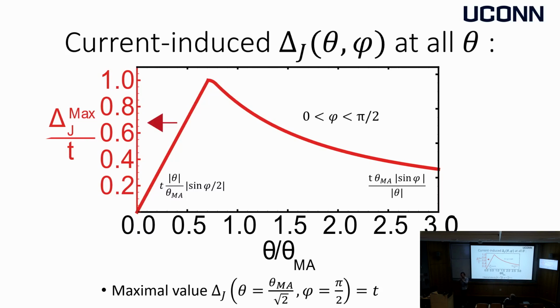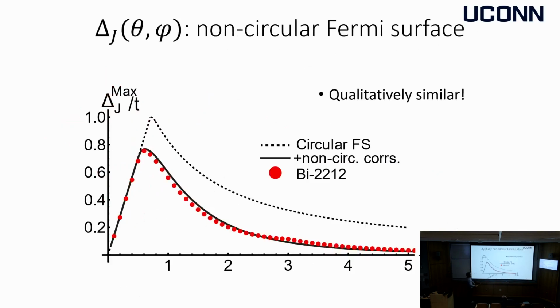This is for a very specific model with a circular Fermi surface. If you take a more realistic one, appropriate for BSCCO, you don't see too much of a difference. The main difference is that at large twist angles, the gap goes down dramatically, but the maximum and the width of that peak do not change a lot. So it's a very robust feature. This topological gap is present at a range of twist angles, and unlike graphene, where if you miss your magic angle by 0.1 degrees, you're done, here you miss it by 0.1 degrees, you couldn't care less.